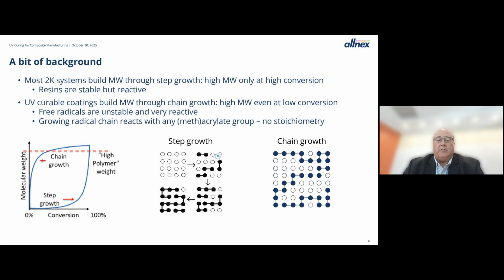UV curable coating resins build molecular weight through a chain growth process. We get high molecular weight even at low conversions. Part of this is because free radicals are unstable and very reactive, and the other part is that the growing radical chain ends can react with any other acrylate or methacrylate group. There's really no stoichiometry involved. So you get high molecular weight right away, and then continue building a high molecular weight as the reaction increases. But you do get the high molecular weight almost instantaneously, and this is why UV is such a fast cure process.